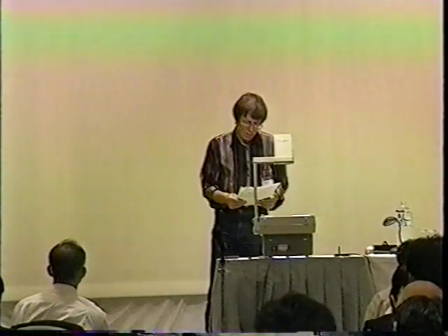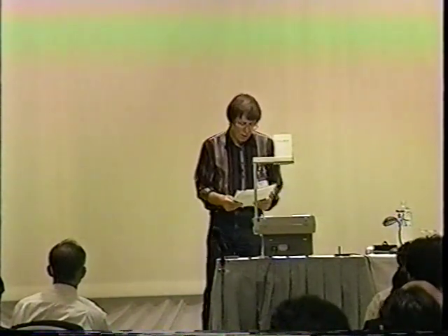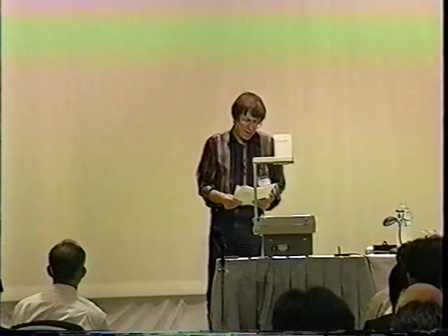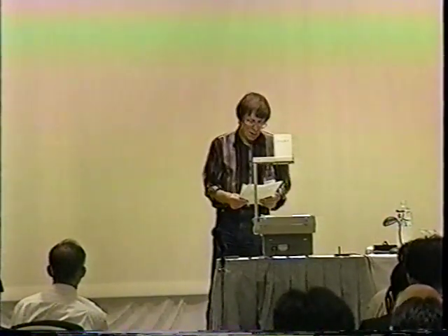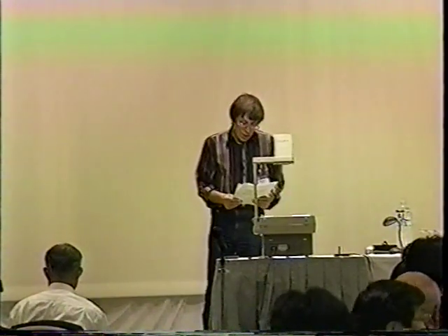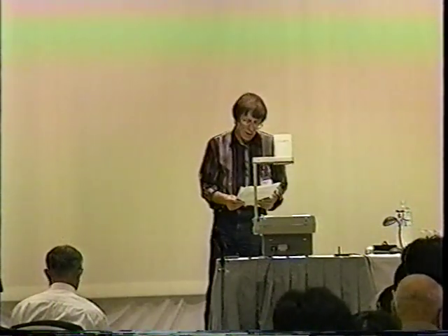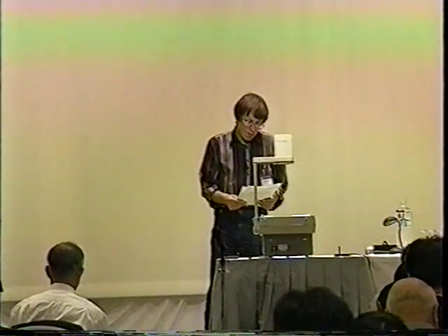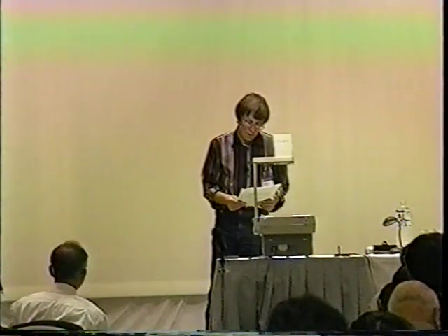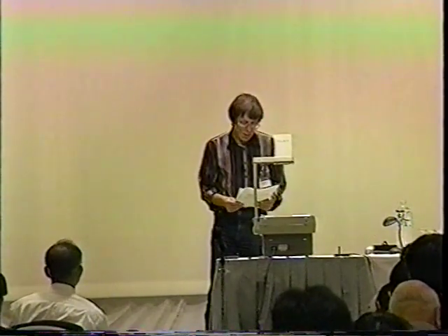The first type is formation of radioactive nuclides, which are observed practically for all working gases, including argon, and cathode samples from the majority of metals, with intensity 10^2, 10^3 per second per cm^2. The second type is a reaction proceeding for some metals with hydrogen, deuterium, with intensity 10^11, 10^12 per second per cm^2, forming stable nuclides with excess heat without acceleration and radiation. Is that all?